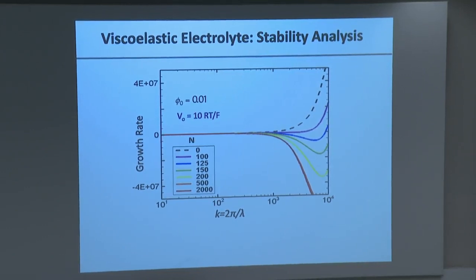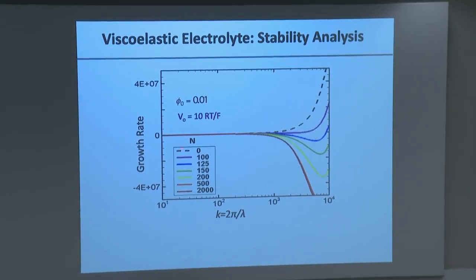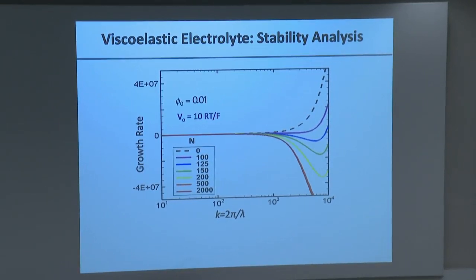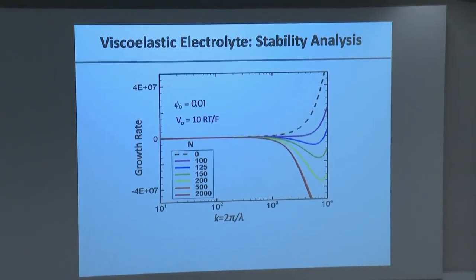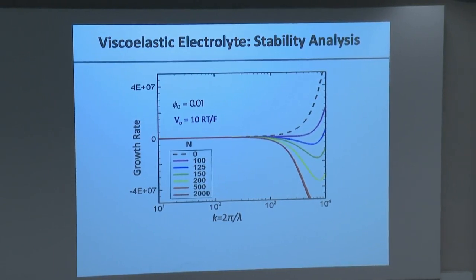And this is called the wave number, okay? And you can see what occurs, right? So when there's no polymer, zero, the growth rate initially is close to zero and then it diverges, meaning the system is unstable. As we increase to 100, same thing happens. But when we get to about 500 or 2,000, the thing is completely stable. So it's telling us that my hypothesis at least has support from theory. The theory tells me that my hypothesis, that the polymer should be able to selectively stop the perturbations from growing, the bumps from forming, is reasonable, all right?